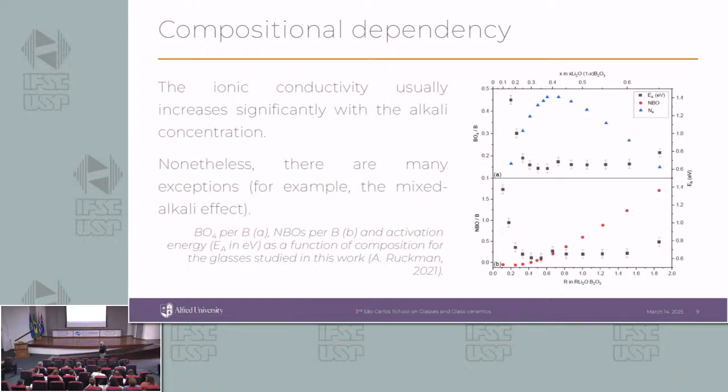Another interesting case is with borate glasses. Being the last one, or one of the last ones, in the last session has its advantages because I can just quote the previous speakers, and if you don't remember, that's your fault, not mine. We already discussed the idea of the boron anomaly, and you can see that for borates, especially on the first graph, I have a decrease in activation energy with an increase of N4. So here I have a linear behavior of the activation energy, and this is also true for conductivity.